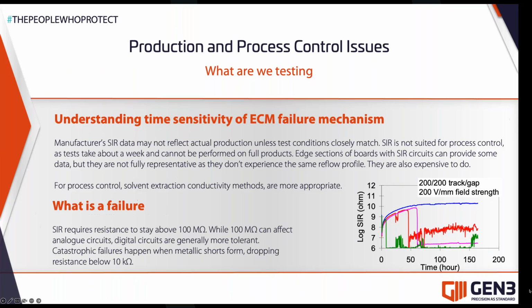When you have snap-off sections of a board with SIR circuits, they can provide some data, but they're not fully representative as they don't experience the same reflow profile. So they're not experiencing exactly the same thermal effects as they would in the center of a board, compared to being at the edge of a board. They're also expensive to do. So for process control, that's where the solvent extract conductivity or ionic contamination, the SEC or ROSE methods, are more appropriate.